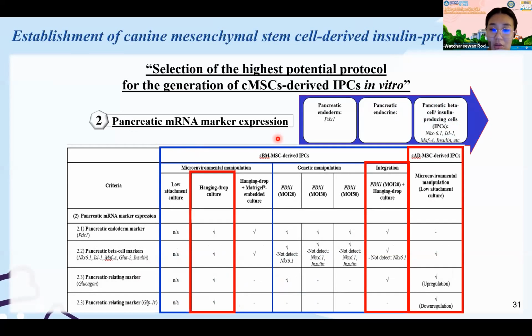The next step is about the pancreatic mRNA marker expression. We found that the IPC from these three protocols can express the pancreatic related marker genes. And the interesting thing is that the integration method of the bone marrow mesenchymal stem cell can upregulate the insulin gene more than the hanging drop culture of the bone marrow, and also the microenvironment of the adipose mesenchymal stem cell.